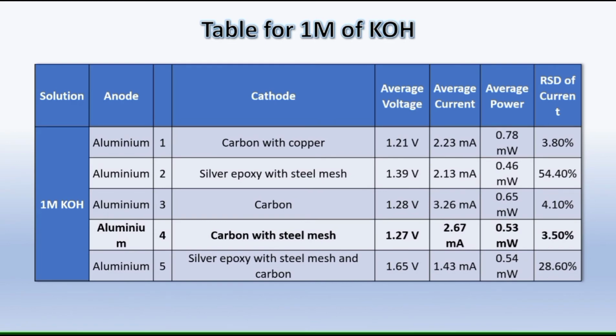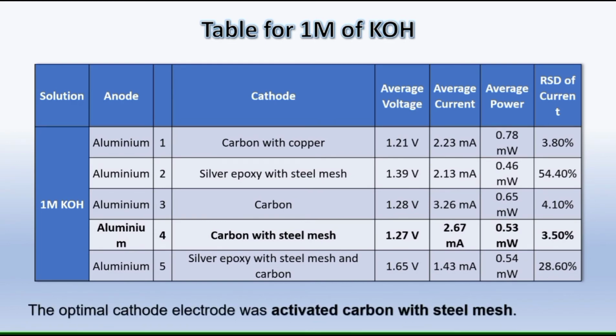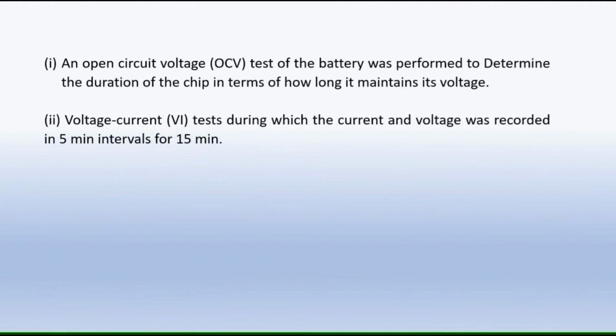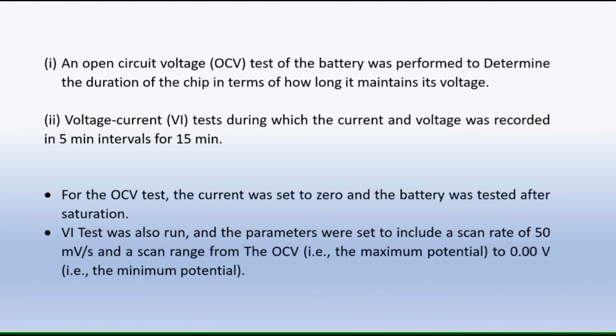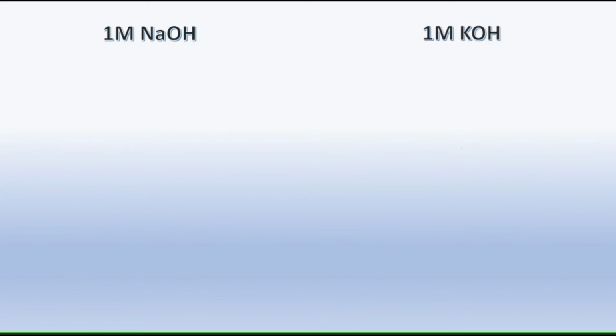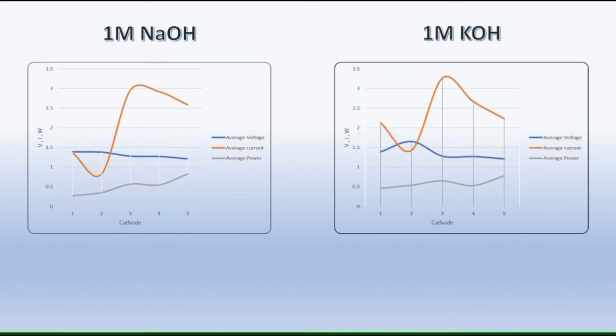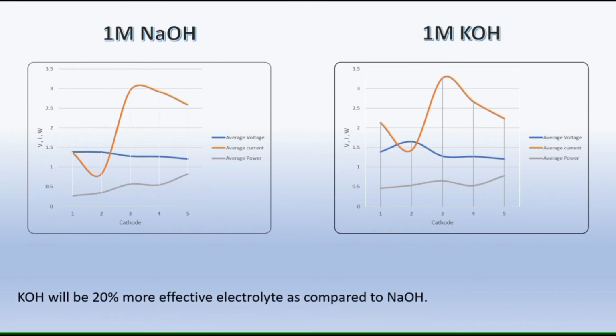In this case, maximum output will be obtained by using carbon with steel mesh as a cathode in the 1 mole of KOH solution as an electrolyte. These two tables are obtained from two types of experiments. First one is an open circuit voltage, OCV, test of the battery, performed to determine the duration of the chip in terms of how long it maintains its voltage. And the second one is a voltage current test, during which the current and voltage were recorded in 5 minute intervals for 15 minutes. Here are the graphs for the NaOH and KOH as electrolyte, which we used in the aluminum air battery. The graphs are derived from the two experimental data which you have seen just now. From the graph, we can conclude that KOH will be 20% more effective than NaOH as an electrolyte.